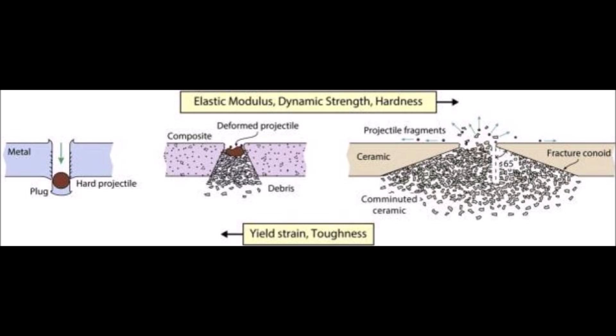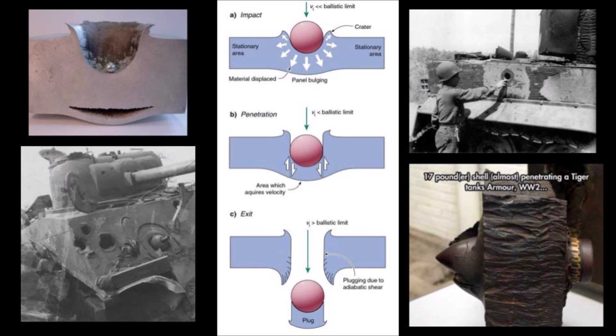What's happening here is all about how energy is dissipated through materials. Since steel is ductile, as it absorbs energy, it begins to deform and slow the projectile, which is good. But energy is not well translated away from the impact site, meaning projectiles are only resisted by the steel directly in line with the surface area of the impact. The more highly force is concentrated, the more likely a thickness of steel will be pushed to failure.